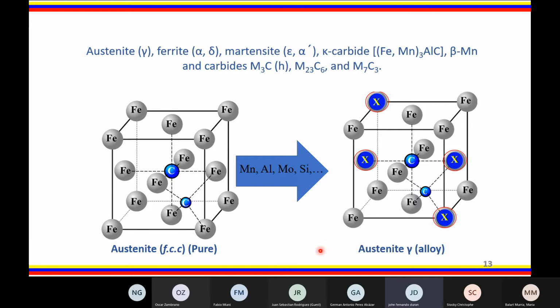Different phases have been reported in FeMnAlC alloys, including austenite, ferrite, martensite, kappa carbide, beta manganese, and other carbides. The figure on the left shows an austenite structure of the steel without any alloy elements. When elements such as manganese, aluminum, molybdenum, and silicon are added, they could replace iron atoms, like shown in the figure, where the X represents the different solute atoms.